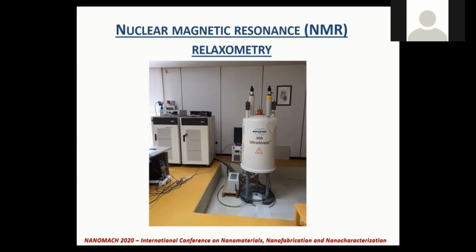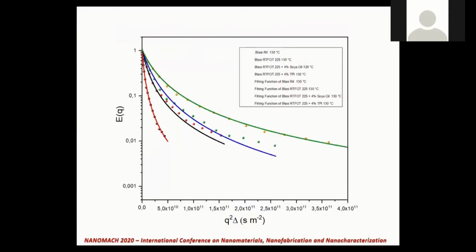So, hereafter, the measured self-diffusion coefficient values are related to the maltene phase. The observation of self-diffusion is based on the mobility of molecules. The motion of these molecules can be hindered due to the obstacles they face during their mobility in the media. The typical data observed where the motion occurs can be considered as a fingerprint of the microstructural behavior. These results are very interesting, but they need a deeper outlook due to the fact that the results obtained were not in line with the expected results.